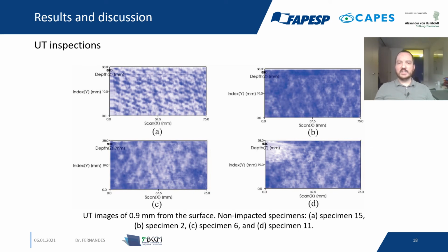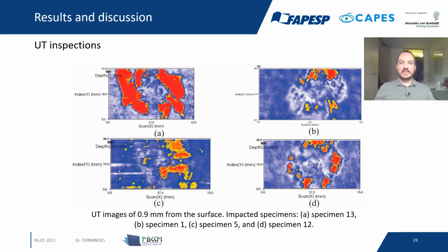The ultrasound inspection here shows some B-scan images. We show some B-scan images here of the specimens that were not impacted. We have specimens 15, 2, 6, and 11. We can observe here that for the specimens that were not impacted, no visible damage is present. But for the specimens that were impacted, the damage is clearly visible, and we have more damage when we have more thermal shock cycles.